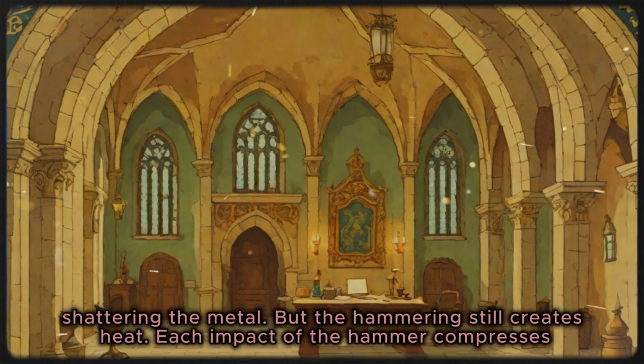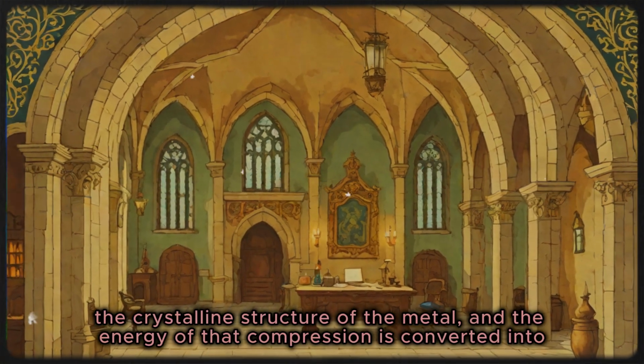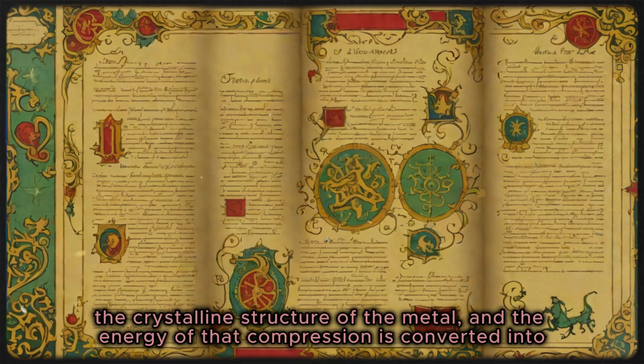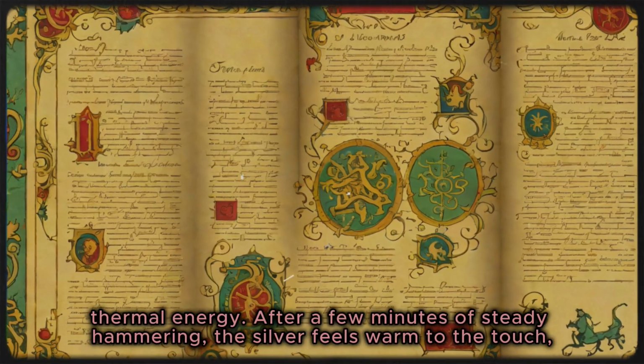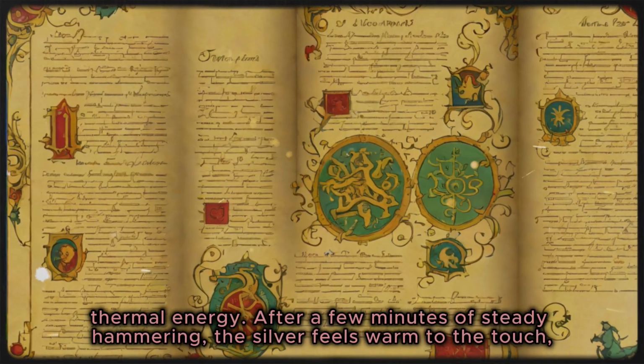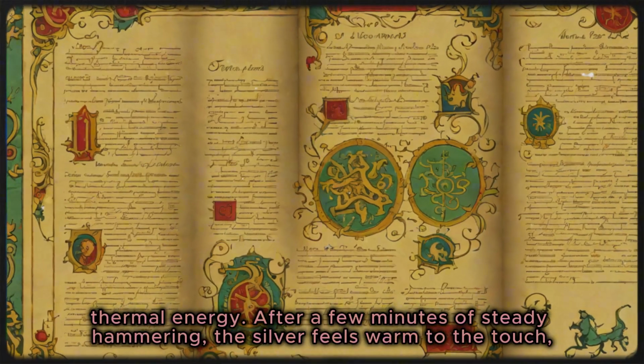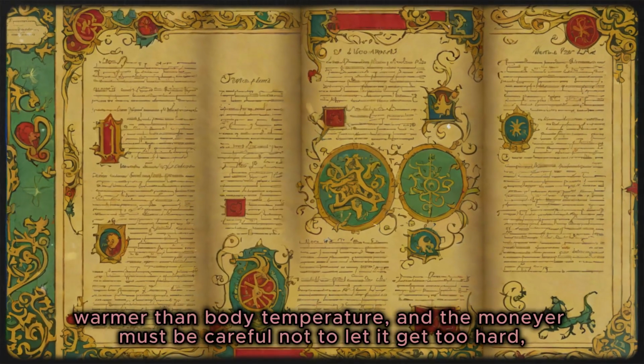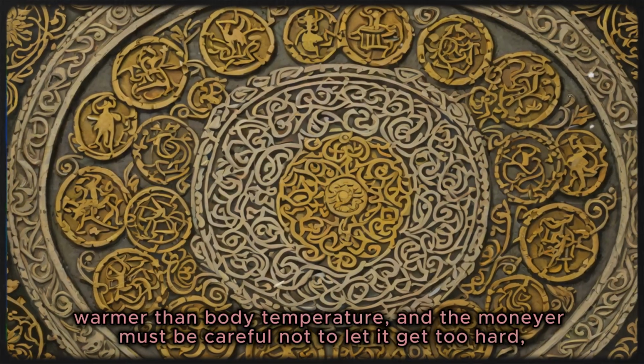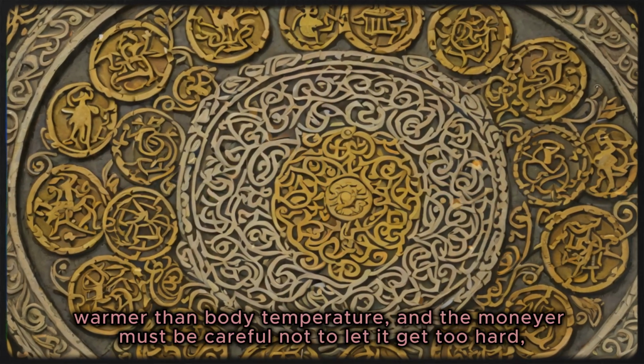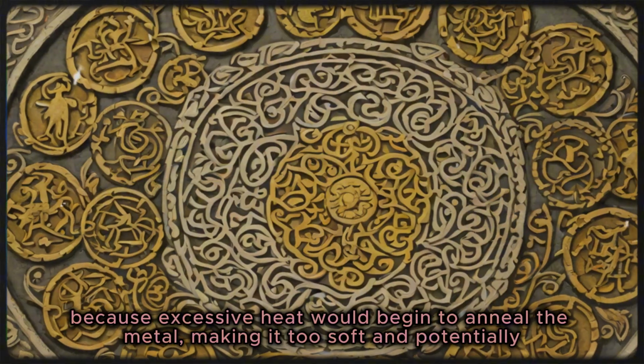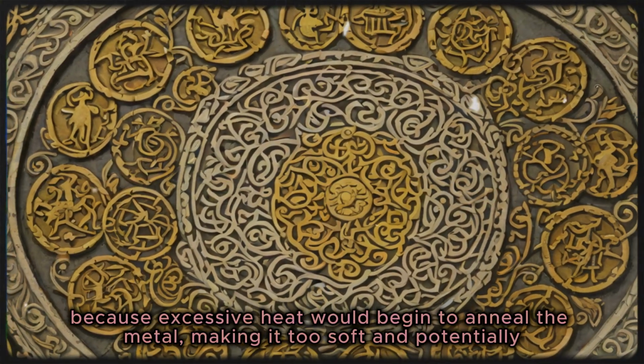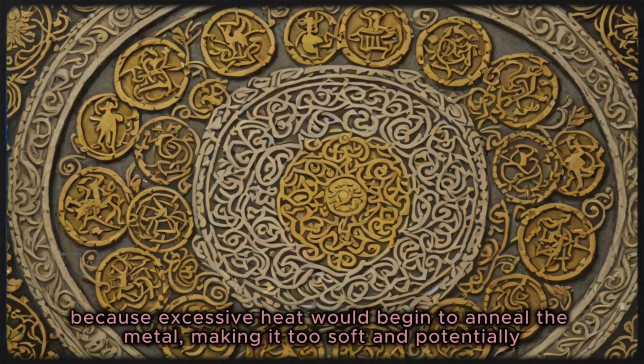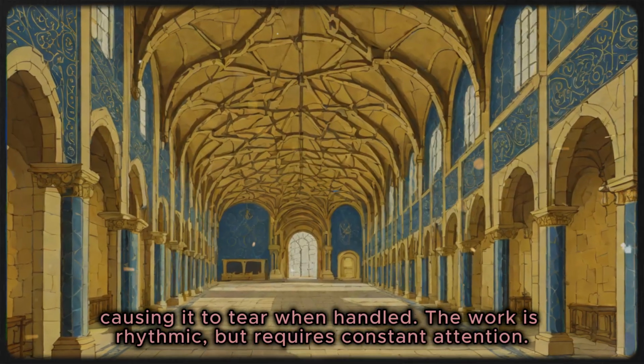Each impact of the hammer compresses the crystalline structure of the metal, and the energy of that compression is converted into thermal energy. After a few minutes of steady hammering, the silver feels warm to the touch, warmer than body temperature, and the moneyer must be careful not to let it get too hot, because excessive heat would begin to anneal the metal, making it too soft and potentially causing it to tear when handled.